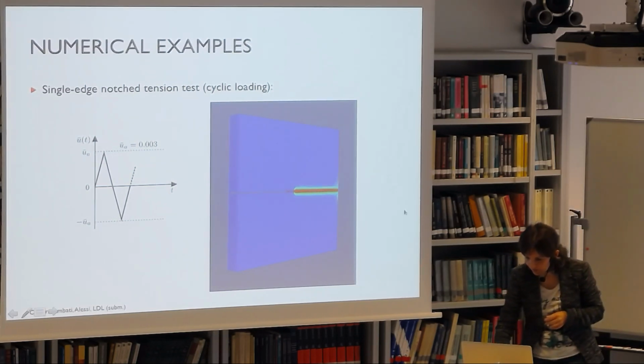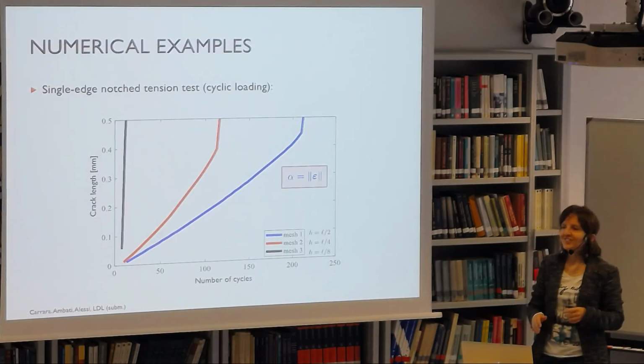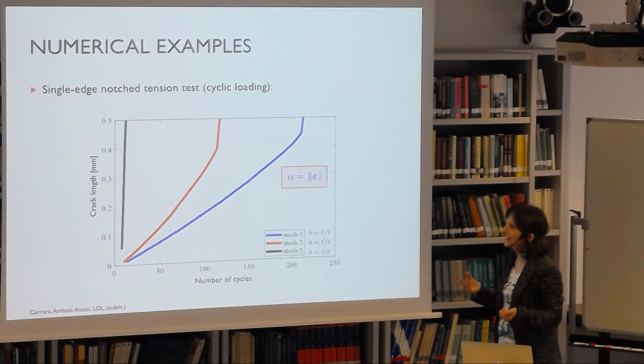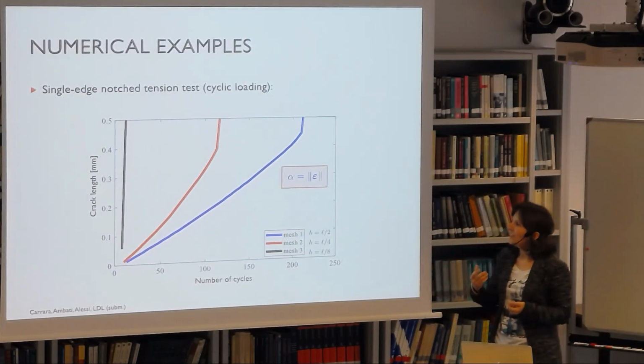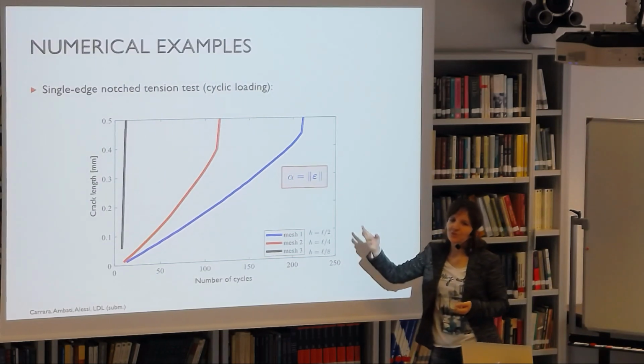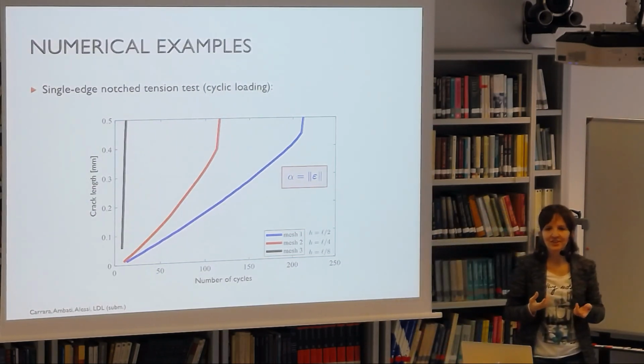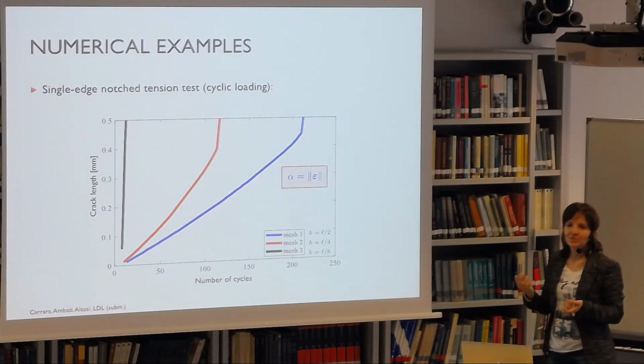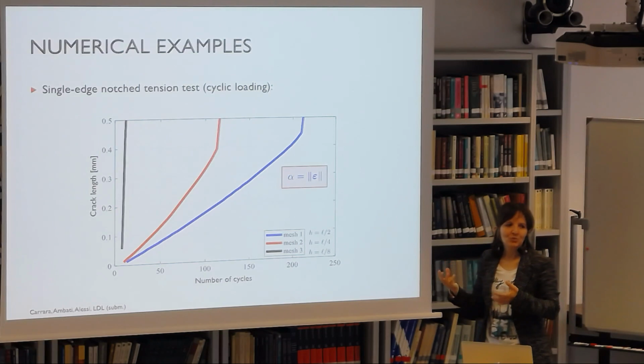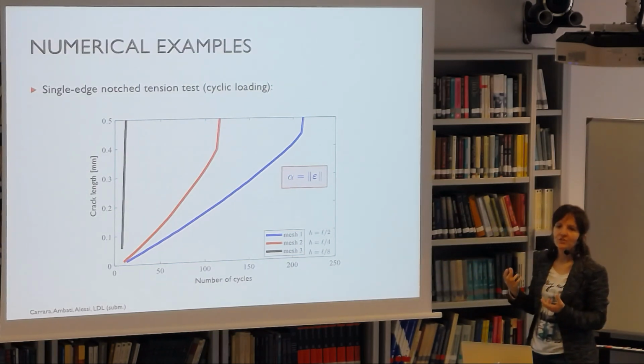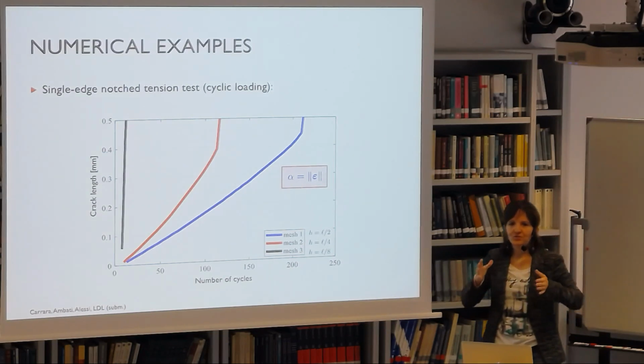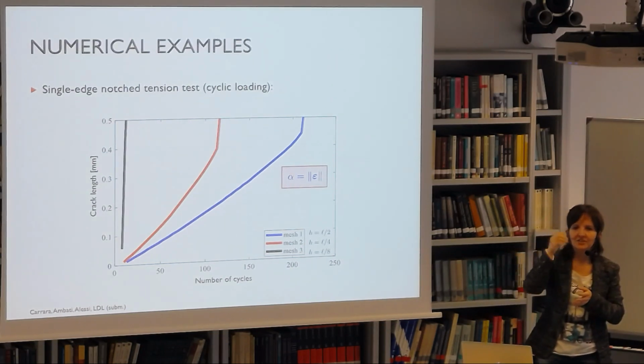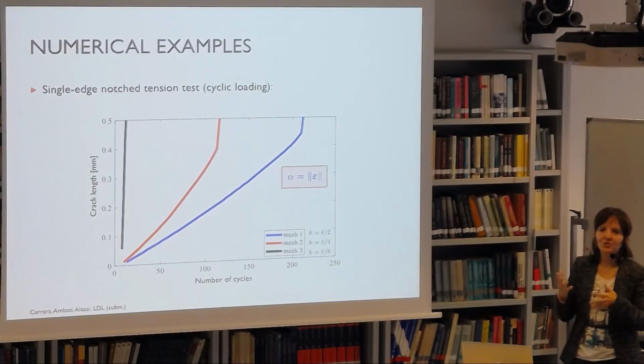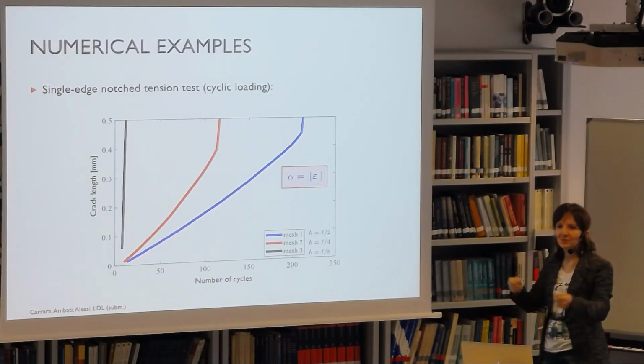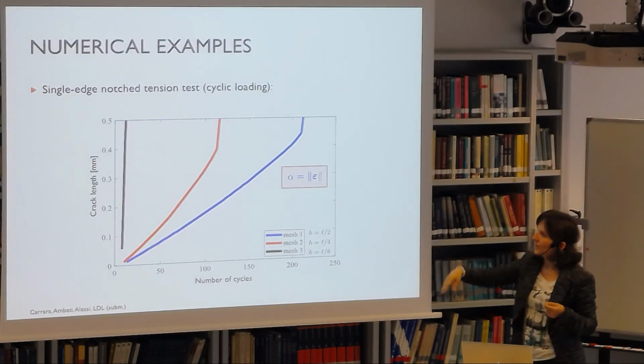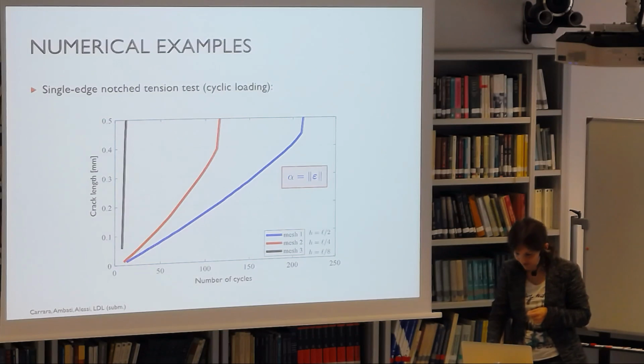But then the first check we made was mesh insensitivity, and we found out, perhaps not surprisingly, but at the beginning we hadn't thought about this, that if we use as cumulated variable some norm of the strain tensor, since the strain is still singular, then of course what we get will depend on the mesh. So choosing as cumulated variable a strain measure is not good, because of course as you refine, your mesh is finer and finer, you capture a singularity better and better, and so you get a faster and faster accumulation of alpha, and therefore your fatigue effect becomes stronger and stronger, and in the limit you get an instantaneous propagation of the crack due to fatigue.